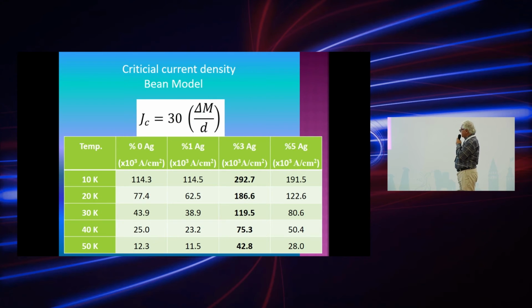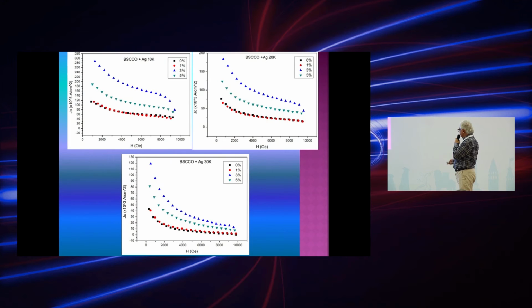Now we have calculated critical current density by using the Bean model, and the formula is given like this. Again, for all temperature intervals, we have calculated and tabulated the graphs. You can see the best critical current density belongs to 3% of silver, as you see in our graph. I would like to show this part: pure, 1% of silver, and in comparison, 3% of silver is almost 2 times larger than the pristine one.